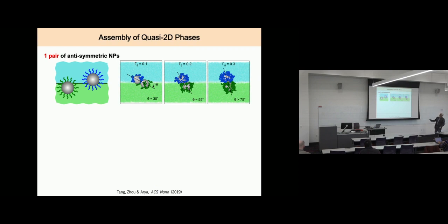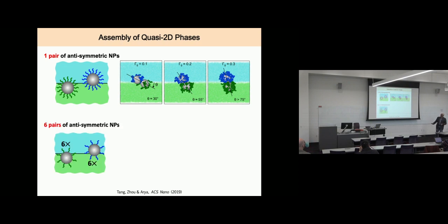It turns out, actually, these dimers, by the way, are actually stable. So these guys are not actually going to assemble because they have a nice steric coat of polymers around them, that if you try to bring other guys in there, it's going to introduce entropic repulsion because you're squeezing these polymers together into a tiny confined gap, which it doesn't like. Okay, but these guys at low density or intermediate density will start to assemble, actually. Okay, they're never going to form stable dimers like this. Okay, so that's what we did. So we took basically just 6 of these, of each of these, rather than 2 of these at these low densities.